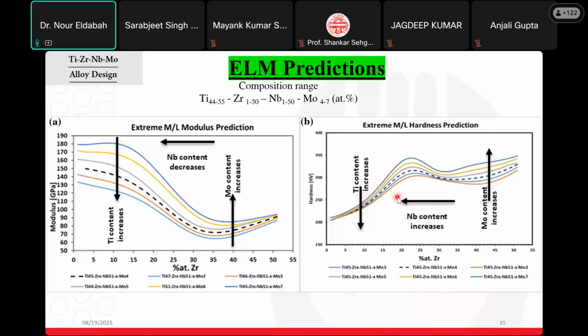After reaching optimum training conditions, our neural networks are tested, and the testing error is very low. We start to feed our neural networks, or in simple words, we start to ask our neural networks about different alloy systems. Every line in this graph represents an alloy system. What will happen to the elastic modulus if we increase the molybdenum, reduce the niobium, or increase the titanium? These graphs give us a clear answer for the change in chemical composition. This answer comes from the machine learning itself.